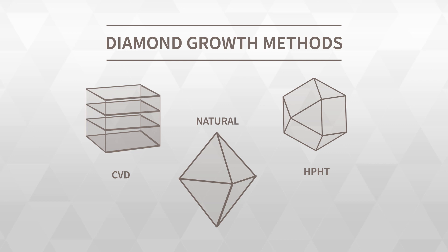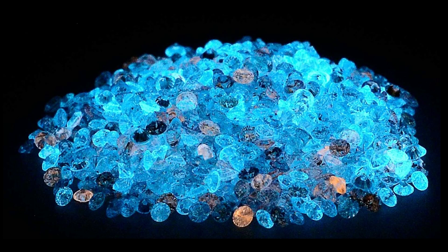The differences which result are optical as well. One of the primary and simplest methods to detect lab-grown diamonds is to shine short-wave UV light into the diamond. Natural diamonds are inert under short-wave UV, but lab-grown diamonds will fluoresce or phosphoresce, usually a teal or orange color.